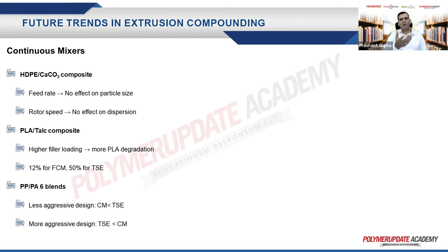So there are some experiments, again you can find it out regarding HDPE with calcium carbonate. The feed rate will have no impact on the particle size, and particle size is very important from the morphological perspective. And rotor speed doesn't have any impact on the dispersion characteristics, breaking it down. Then PLA talc, higher filler loading. When we are talking about adding talc in PLA, which is polylactic acid, you find with higher filler loading, more PLA degradation would be observed. And 12% is there for FCM and 50% for twin screw extruder.